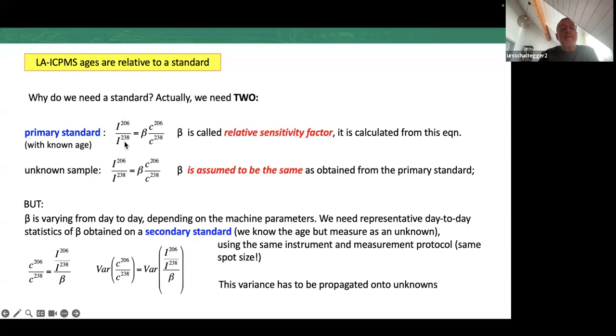And then we realize that actually the intensity ratio 206 to 238 is not equivalent to the age we should get. We have fractionation in the laser spot during the transfer and then also in the mass spectrometry. So the concentration ratio, which gives us the age, is not equivalent to the intensity ratio we measure. So we have to establish this correction factor, beta, which is called the relative sensitivity factor. It is calculated from this equation. And then we apply this to another sample.